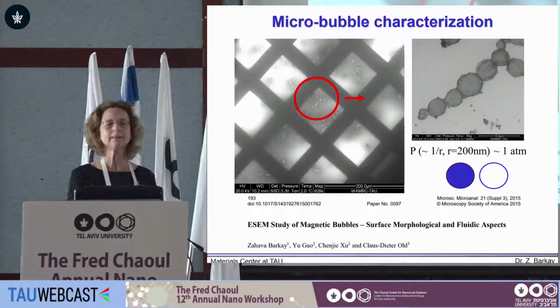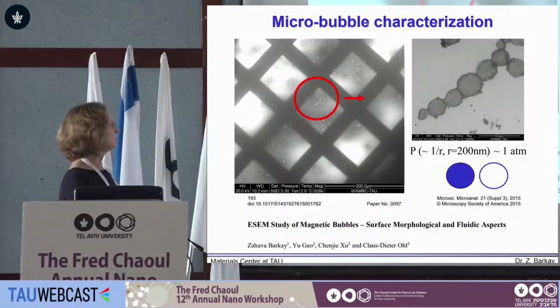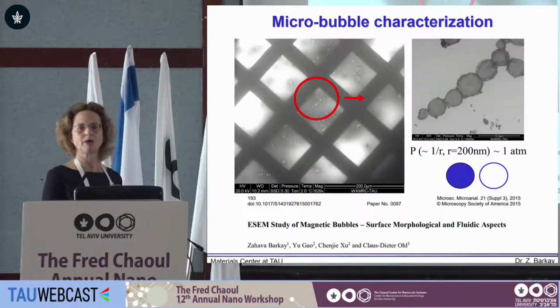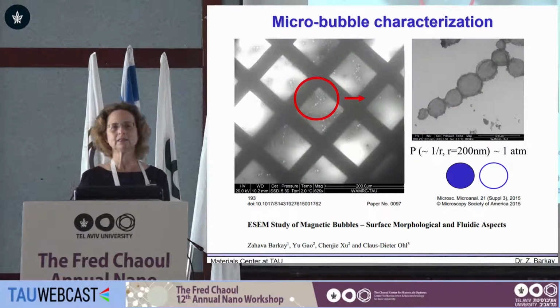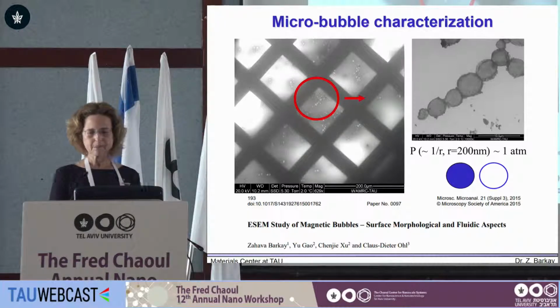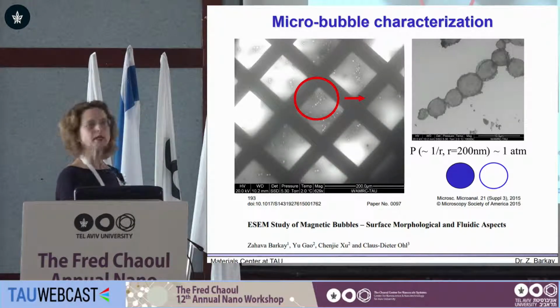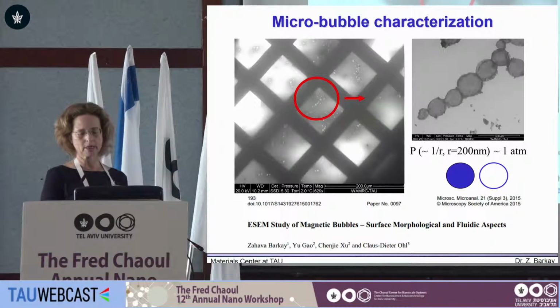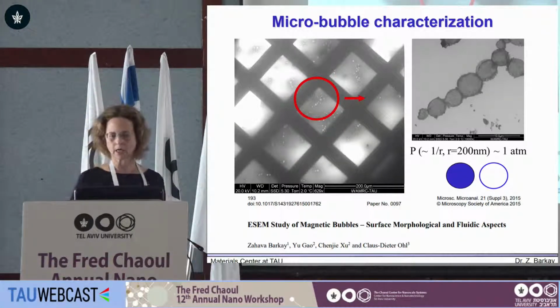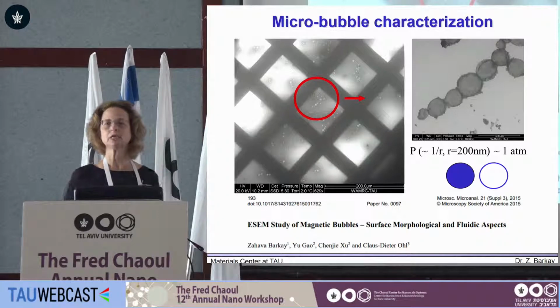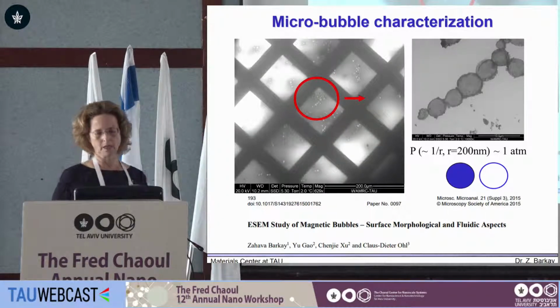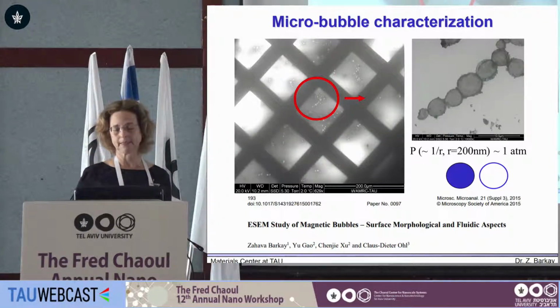We can see that these bubbles actually survive at the length scale of imaging - let's say seconds, it can survive for minutes. And at low magnification you can see that these bubbles are of microscale, and they actually have a shell, a magnetic shell, because they are used for ultrasound applications and biological applications.